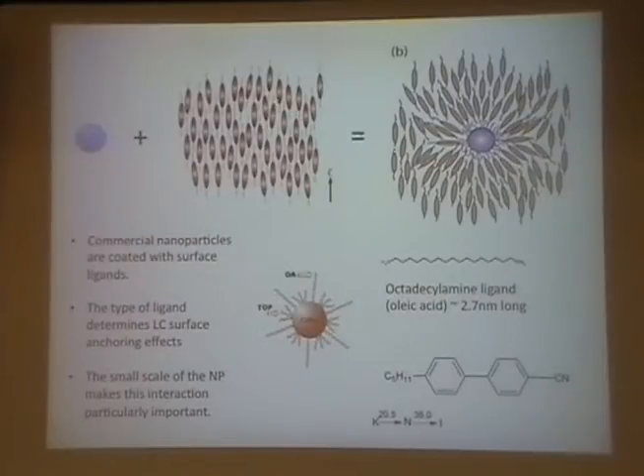Okay, on first pass, that's what you think might happen. However, it's not necessarily going to be the only thing that happens. But this is one thing that can happen. Just another diagram demonstrating the surface. Also, these ligands can increase the size of the particle quite a bit, by a couple of nanometers at least. So the type of ligand on the surface really controls the anchoring effects and how the liquid crystal will orient around the particle. Another point here is the small scale of the nanoparticle makes this interaction particularly important.